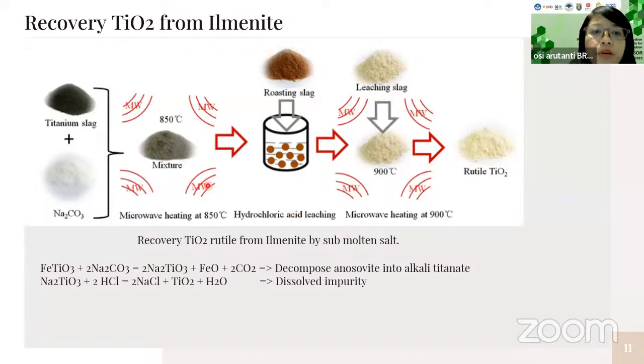Here we can use a temperature below 1000 degrees Celsius, while if we use the conventional method, we use a temperature above 1500 degrees Celsius. And here we only use a process time from 30 minutes to 3 hours, but with the conventional method, usually we use above 5 hours, longer than 4 hours.